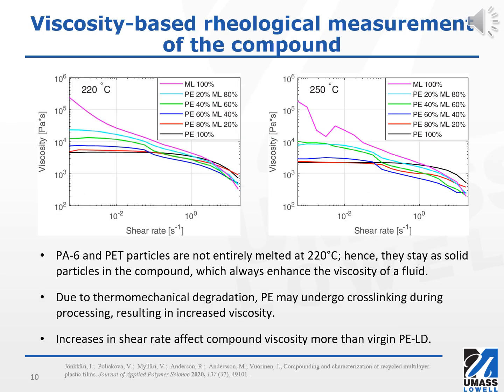So this slide provides an illustration of the rheological measurement of the compound based on its viscosity. Because polyamide and PET particles don't completely melt at 220 degrees Celsius, they continue to exist as solid particles within the compound. This significantly increases the viscosity of the liquid. During the processing stage, polyethylene can suffer from thermomechanical degradation, which can lead to cross-linking and an increase in the viscosity. An increase in shear rate has a greater impact on the viscosity of the compounds than on that of virgin LDPE.